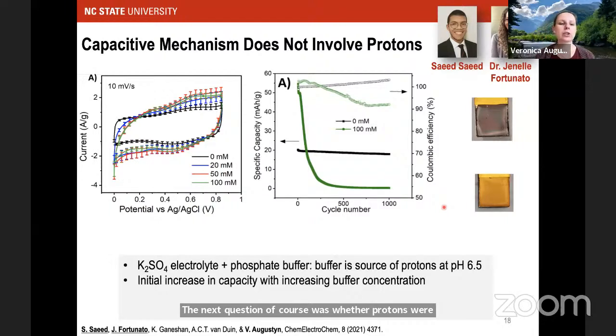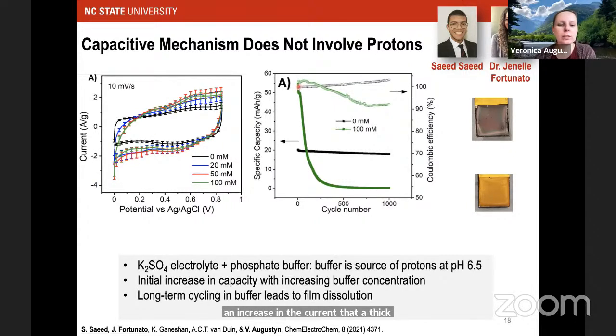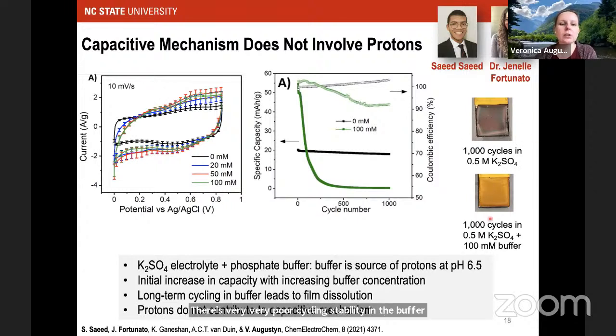So what we did here is we took our potassium sulfate electrolyte and added phosphate buffer, where now the buffer is a source of protons at a fixed pH that does not lead to the dissolution of the birnessite. And what we found is that while there's an initial increase in the capacity, so you can see that as an increase in the current at a fixed scan rate, there's very, very poor cycling stability in the buffered electrolyte, and that comes with dissolution. So what that means for us is that the capacitive process that we're seeing is really cation driven, and it's particularly driven by small cations like potassium.